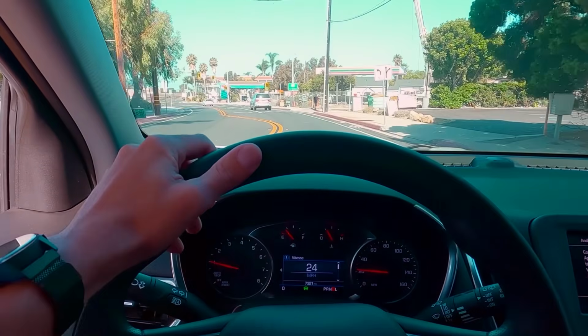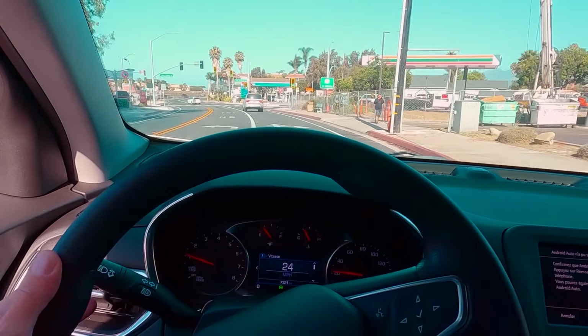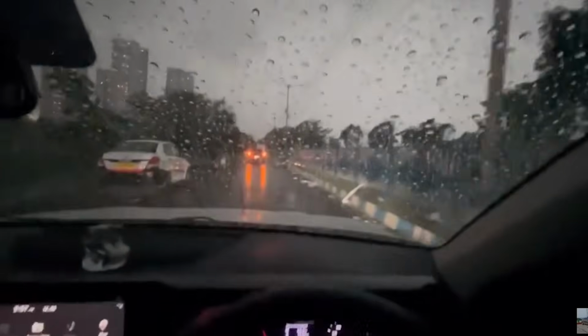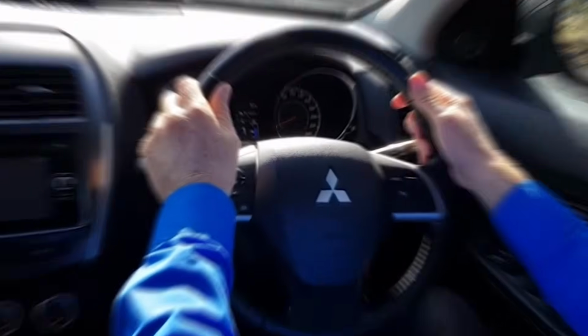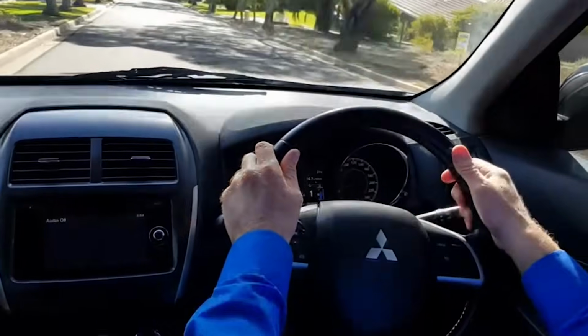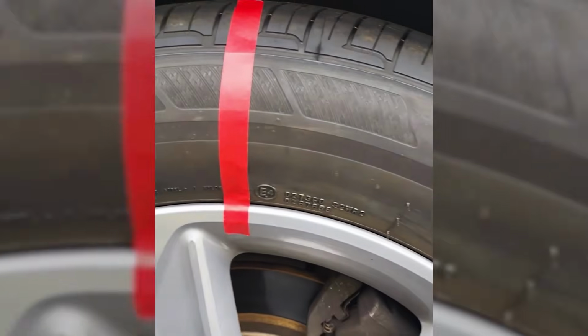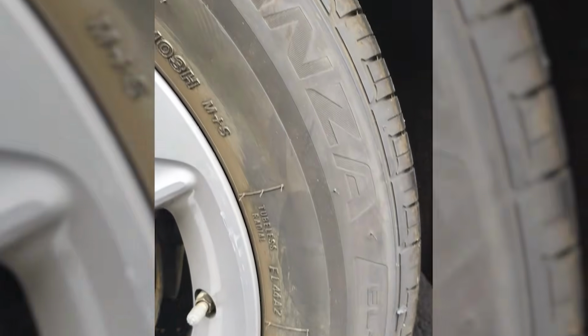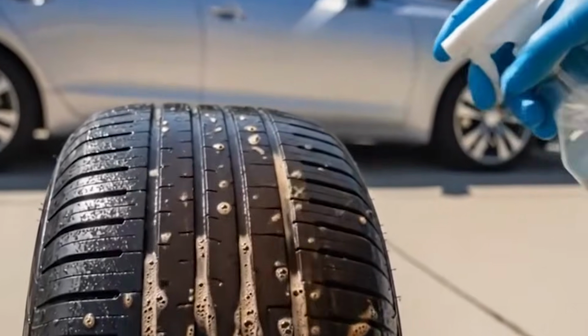And then here's the part that genuinely surprised me when I ran this test for the first time. 2 weeks later, after 2 washes and a rainstorm and daily driving, the tire looked essentially the same. Slightly less intense, sure. Nothing lasts forever, but nowhere near the complete fade out I'd see from tire shine after a single rainstorm. Because the glycerin isn't sitting on the surface waiting to wash off. It's inside the rubber. Let me show you the comparison I ran on my own car.